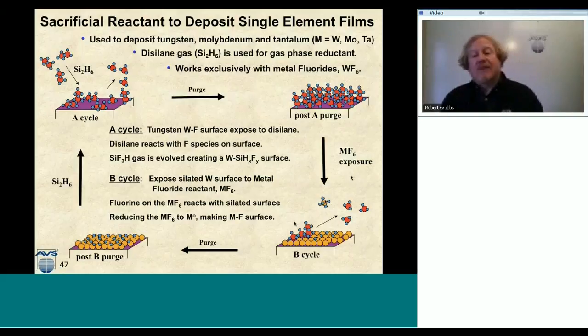And at the same time, it actually reduces the metal from the plus oxidation state down to the 0th oxidation state or the +1 metal oxidation state, and leaves behind a metal fluoride surface. Now I have this metal fluoride surface, then I can expose it again to disilane, creating this fluorosilated species over here. And then once I have this fluorosilated species, I come in with the metal hexafluoride, and then this fluorosilated species actually reduces the metal fluoride gas down to the metal oxidation state of 0 or 1, again, leaving behind the fluorinated metal fluoride surface as a reactive handle for this disilane chemistry.